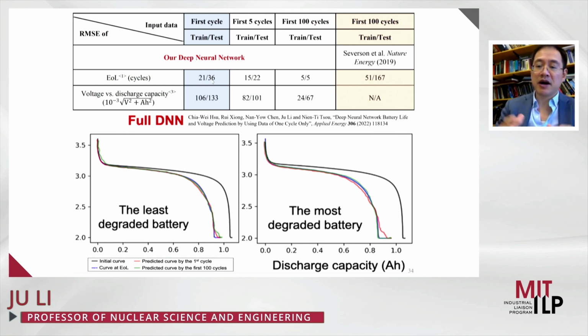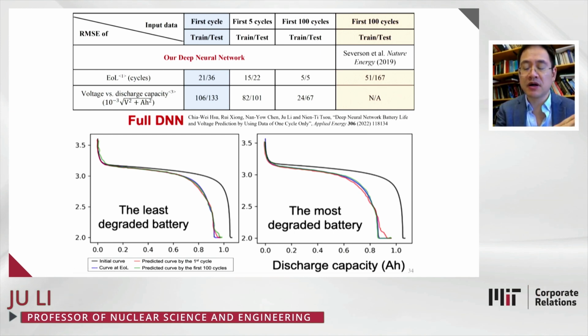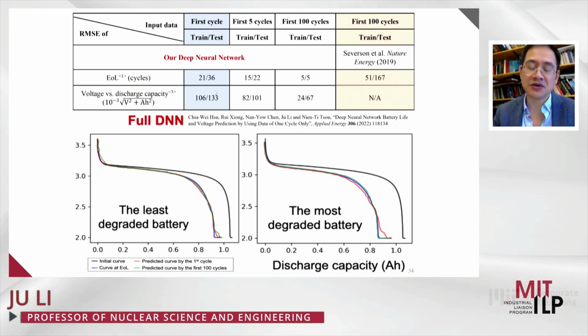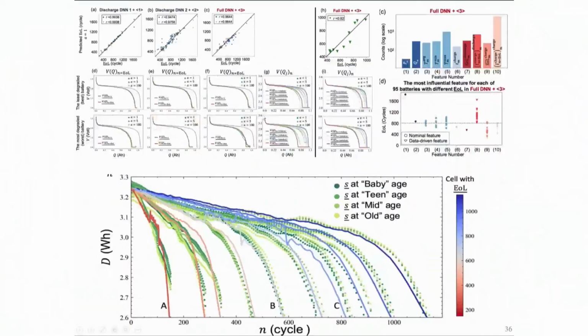So in other words, given a bunch of lithium iron phosphate batteries, some of these were heavily used before or even abused. Some of these were lightly used, but just doing one cycle of test, we're able to predict this battery has 1,200 cycles residual life, but that battery has only 300 cycles left, to an error of plus minus 20 cycles. And not only the residual life, but we're also able to predict the cycle by cycle voltage capacity curves. And this model was shown to be much better than human expert design features.